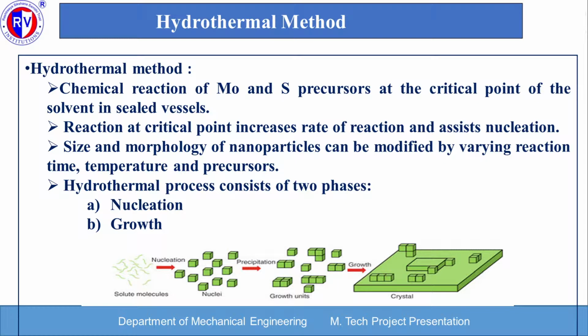First step in our project is the preparation of nanomaterials. It is done by the hydrothermal method. In this method, chemical reaction of molybdenum and sulfur precursors occurs at the critical point of the solvent in sealed vessels. Reaction at the critical point increases the rate of reaction and assists nucleation. Size and morphology of nanoparticles can be modified by varying reaction time, temperature and precursors. The hydrothermal process consists of two phases: nucleation and growth. As you can see in the figure, here the nucleation starts, the nuclei are present, precipitation occurs and the growth of the crystal occurs.